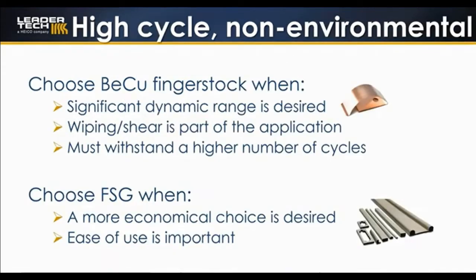Beryllium Copper Fingerstock is made from beryllium copper sheet metal, formed to the desired shape and heat treated to maximize the strength of the material. Choose beryllium copper when significant dynamic range is desired, wiping or shear forces are part of the application, or if the gasket must withstand a high number of cycles. FSG is extruded polyurethane foam with conductive copper nickel fabric wrapped around it. FSG gaskets are a more economical option than beryllium copper and are simply applied with a pressure-sensitive adhesive where you need them.